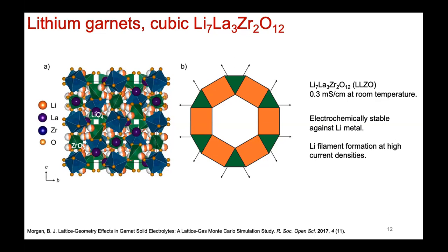It's stable, but if you try to charge and discharge too fast, this ceramic material, right, it's still porous unless you densify it. So that's what people try to do. So the lithium filament will actually still grow and your battery will still eventually short. And why I call it lithium filament as opposed to the lithium dendrite is because dendritic formation is a function of the solidification process, which is a liquid to solid process. Here, all of the materials are solid. Okay. So you have lithium filament growth. You don't necessarily have dendritic growth, but it's a technical definition of what a dendrite is.